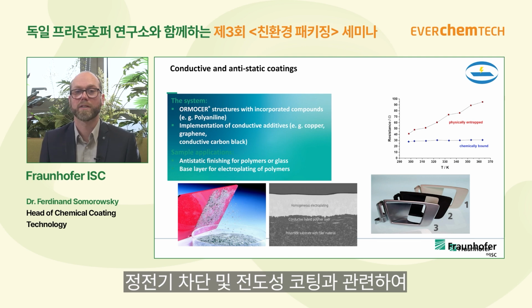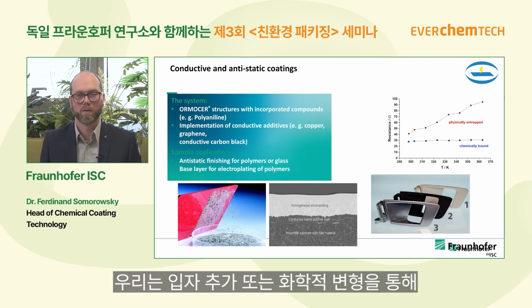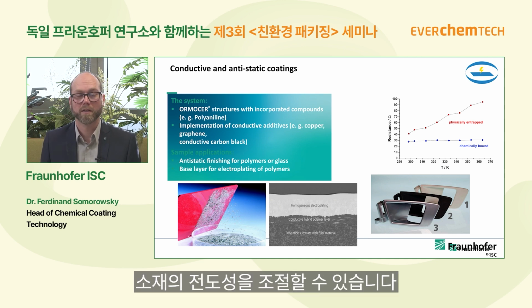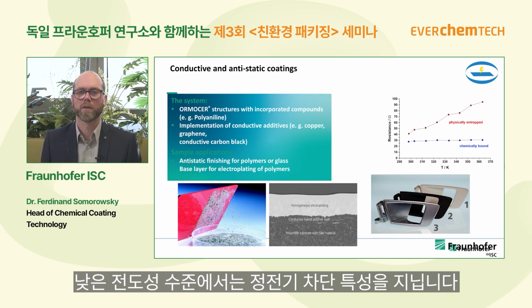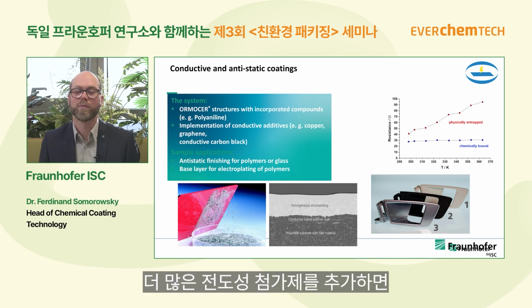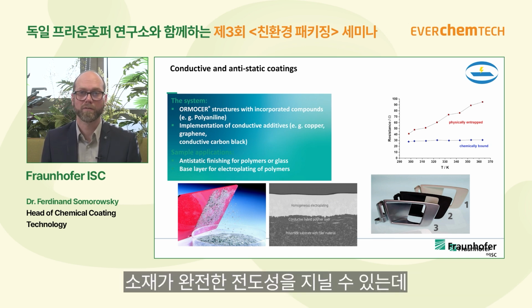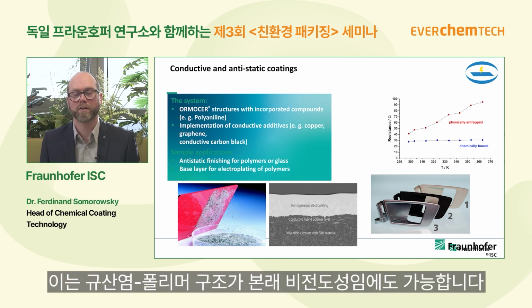Anti-static and conductive materials: we can integrate a certain conductivity by particles or by chemical modification, and in the lower range the coated surface shows anti-static behavior. When we integrate more or other additives, it can even be conductive, even though the normal Ormocer, due to the silicate and polymer character, is not conductive.